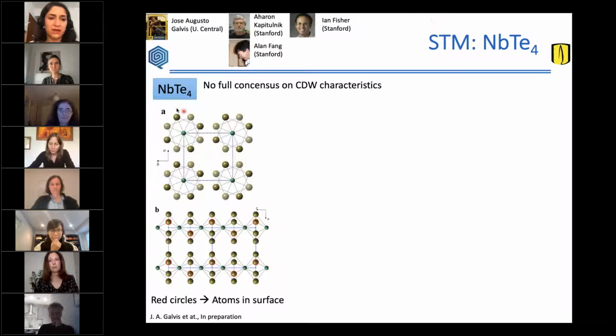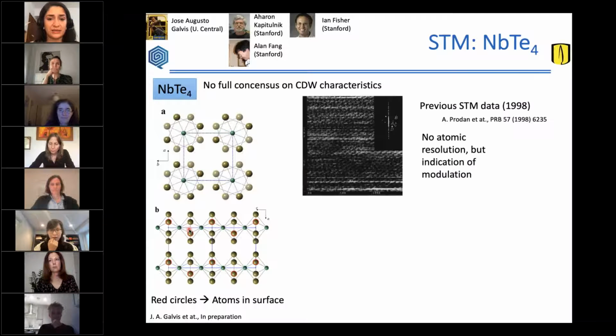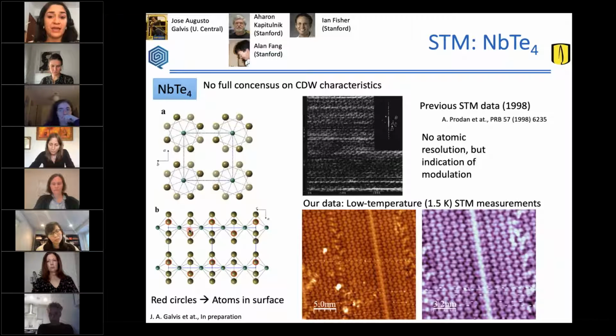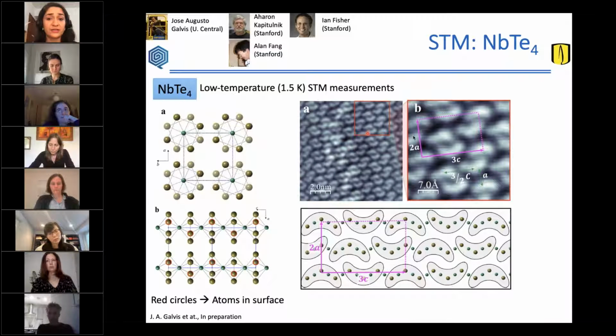So this is niobium tellurium 4, this very quasi-1D material, in which direct characterization by STM of the charge density wave formation has been done previously, but not with the resolution of the tools we have currently available. So we have retaken this problem, and we have observed very beautiful patterns of charge density wave formation for this compound. And we have been able to understand first the superstructure and directly observe for the first time the superstructure formed by the charge density wave in this compound, which is this one here,